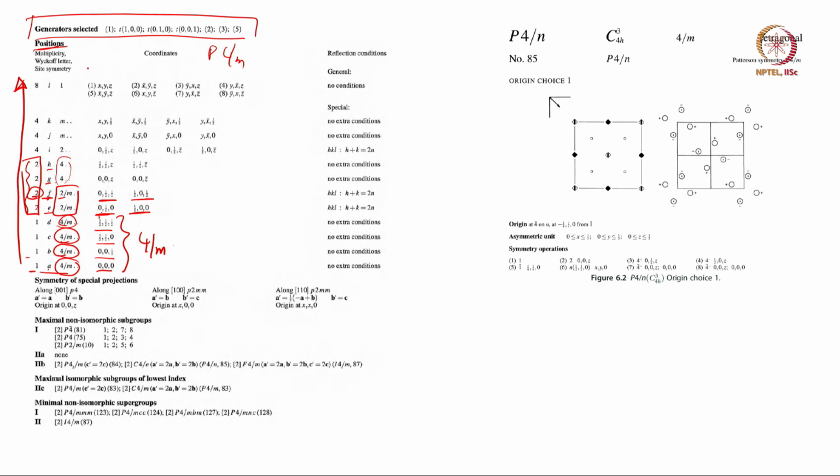So these are all the point group operations that I have, and the one which is just an identity operation exists about any point. If I have x, y, z, the same is the environment about x bar, y bar, z by symmetry. So it will have a multiplicity of 8. So x, y, z is equivalent to 8 different points, and each of these points has a trivial symmetry which is a 1-fold symmetry. That is how you read the tables.